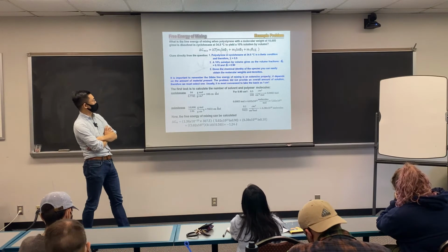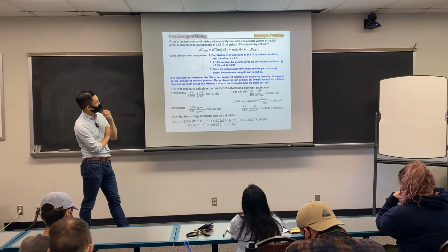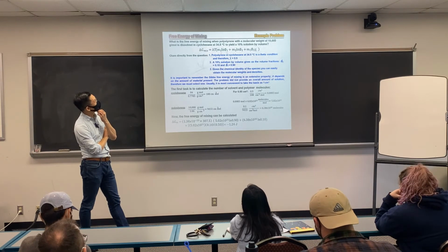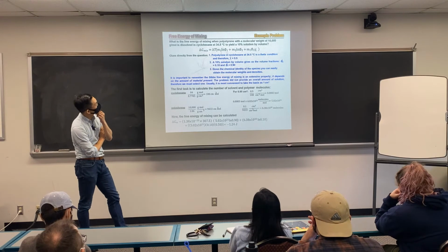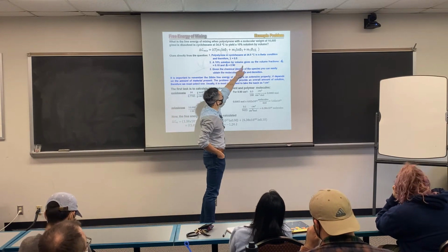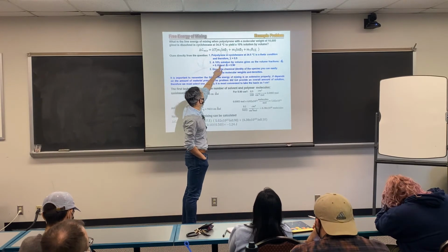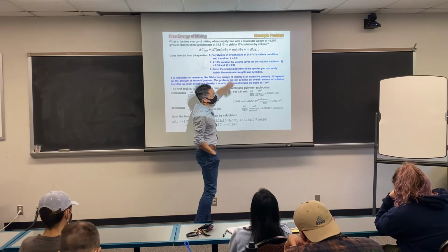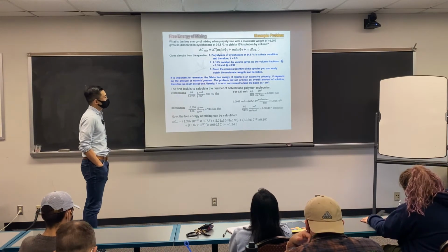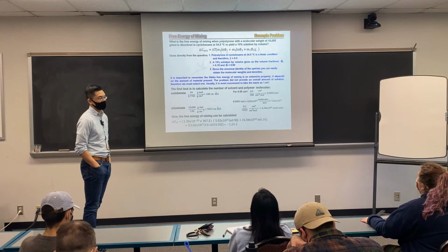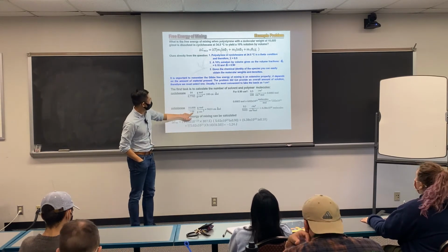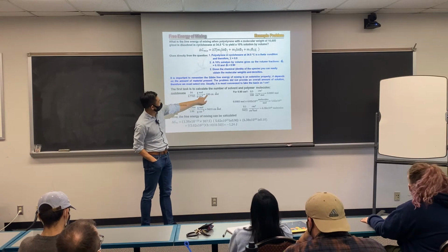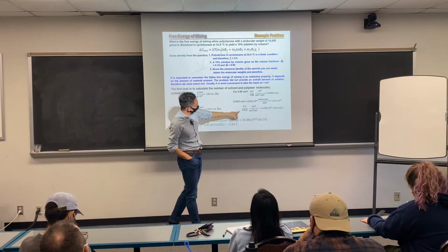Okay, so how do we address this problem? First, we need to get phi 1 and phi 2, and also N1 and N2. We know 10% by volume is given by the equation. So 10% will be phi 2, this is polystyrene. Phi 1 will be 0.9. So how about N1 and N2? How do we convert the volumes to the number of molecules? That requires converting using the density, so you can convert how much volume per mole. So you can use the volume to convert to how many moles, and then to how many molecules.